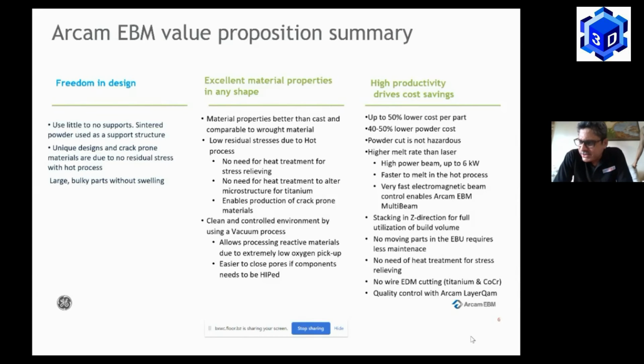And the other most significant benefit of the ARCAM EBM process, which is typically a mandatory requirement in some cases in aerospace as well as in medical, is that if the components are required to be hipped, you have a better choice to have the pores closed with this process of build. Now, these two drive significant productivity benefits for the end user. It's proven over time by many users that the cost of the part is reduced by 40 to 50%. You have lower powder cost because wastage on the supports is low and reuse of the powder is high.